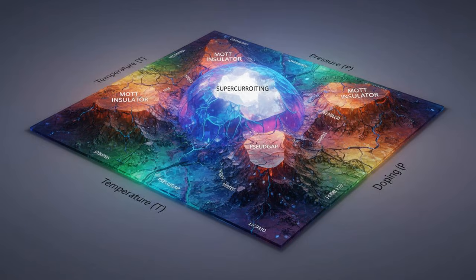Since 2018, we have discovered a zoo of phases in this material. If you plot the behavior on a graph, you get a complex phase diagram. You have the superconducting dome, where resistance vanishes. You have the Mott insulator state. And above the superconducting temperature, you have a strange metal phase, where resistance scales linearly with temperature, a behavior that defies standard quantum theory. But the magic didn't stop at superconductivity.